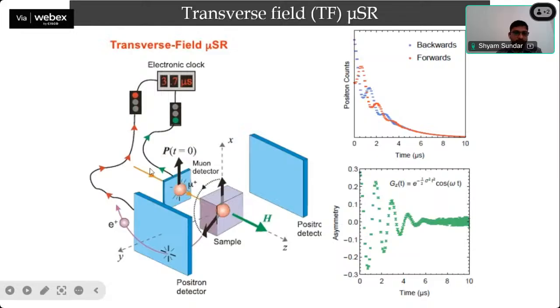Here I'm showing that we apply the Wien filter, by which we change the muon polarization, and we apply the magnetic field along the beam. So the muon spin is this, and the field is in this direction, which are perpendicular to each other. Then the muon spin starts rotating around this applied field, and you decay a positron into either the left or right detectors. In the left or right counters you see these oscillations, and when you take the asymmetry, it gives you oscillations like that, which decay as you go higher in time. If you fit these oscillations, you can tell exactly what the magnetic field distribution in your sample is, how much magnetic field you applied, and how much it is distributed in your sample.